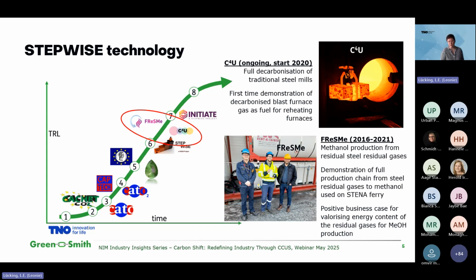In addition, we had the C4U project, where we looked at decarbonisation of the traditional steel mills. And we actually proved within a first-time demonstration that we could use decarbonised blast furnace gas to fuel the reheating furnaces. So in effect, decarbonising the later steps of steelmaking.